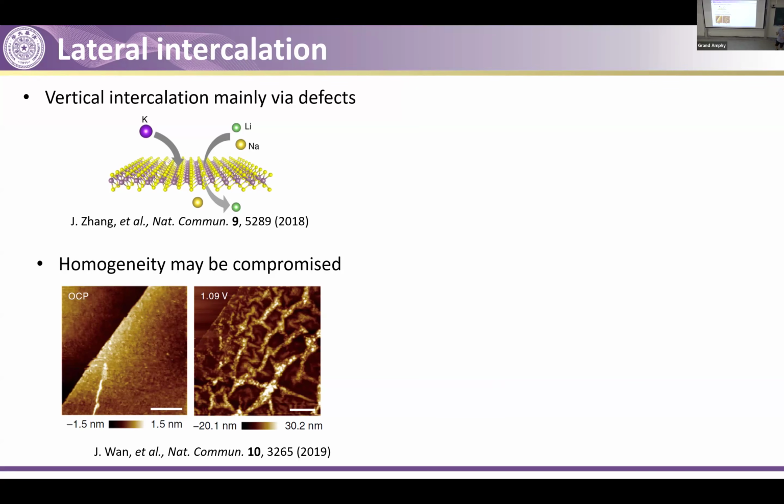The problem is this intercalation is not a very homogeneous process in this particular material. In some materials, it looks quite homogeneous, that we check different contacts and show the same result, but not the case for titanium diselenide. The problem of this intercalation could be that the lithium goes through the holes and defects in the materials. When they push through these holes, they may create some wrinkles or some cracks.